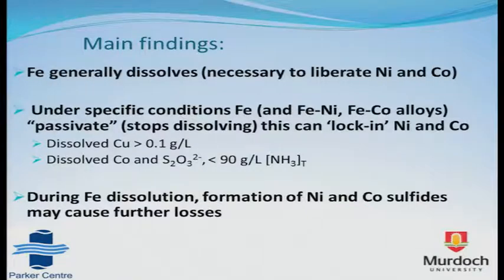So overall, the main findings are that iron in most of the solutions of combinations of the ions present generally would remain active, and this is necessary, as I said before, to liberate the nickel and cobalt.